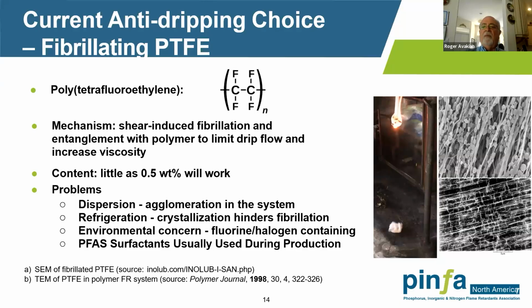And upon being placed in the presence of a flame and heat, these things tend to contract very much like a rubber band does in the presence of a flame. And so it tends to pull the polymer mass away from the flame and inhibit dripping. So this is the mechanism by which it works. It's kind of unique to PTFE. Not much is needed to do this. Contents as little as 0.5% will work. In some cases, you do see it at maybe 1 or 2%.